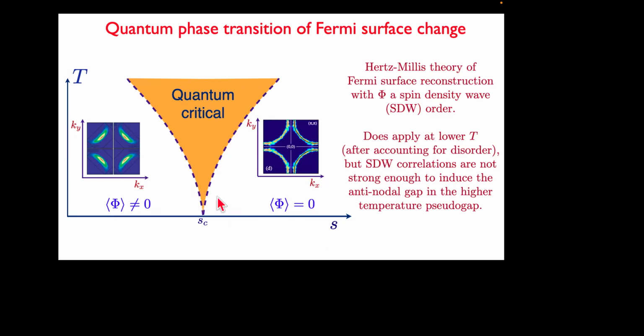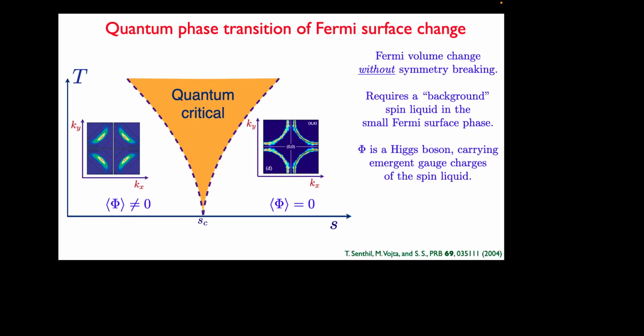But we know from experiments that this kind of spin density wave order is not really present at the higher temperatures where you see the strange metal. So what do you need there? I believe we need a more complicated type of phase transition, which is rather similar, where you get this spin liquid background I mentioned for the pseudogap. So you need a transition from something without a spin liquid to something with a spin liquid in the background, and look at how it reacts to, very crucially, and this has been the key to the recent progress, spatial disorder in the position of the quantum critical point, which is always present in any real material.